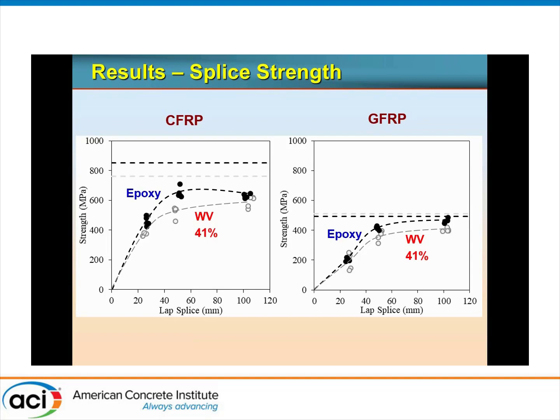Again, the WV product came very close to the epoxy. In fact, the dotted line here is the tensile of the WV. So I would argue that this is fairly comparable to epoxy. For glass, we had better luck approaching the full tensile strength of the material for both the epoxy and the WV resins.